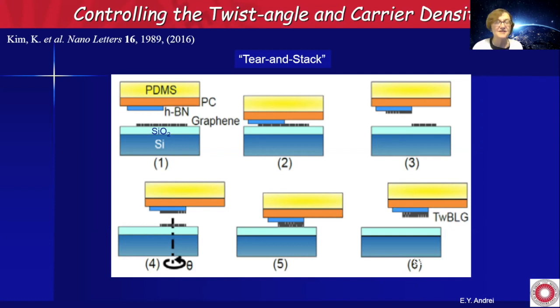So here you deposit a layer of graphene the usual way on a silicon dioxide wafer. Then you pick up, by using these two polymers, a piece of boron nitride. And the boron nitride is critical. This was another advance in the field, because boron nitride is a sister material to graphene. It also has a honeycomb structure. It has roughly the same lattice spacing, but it's an insulator.